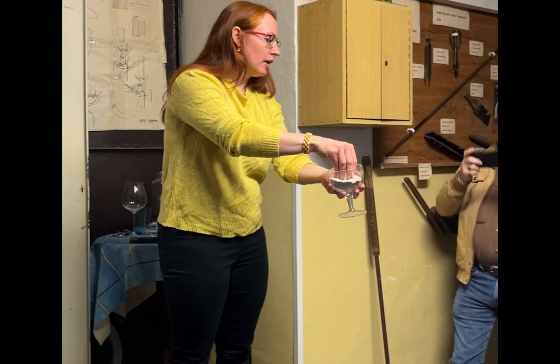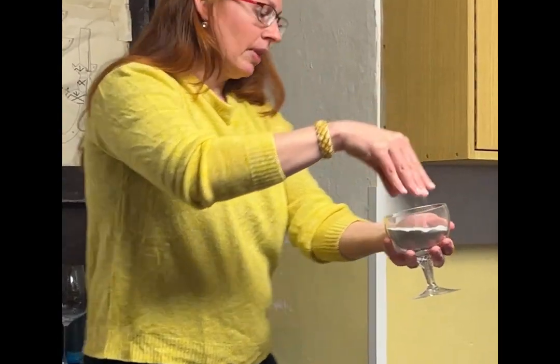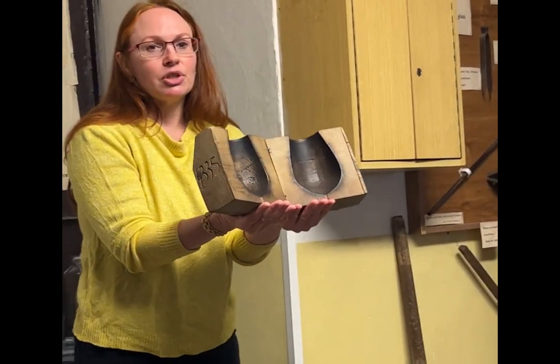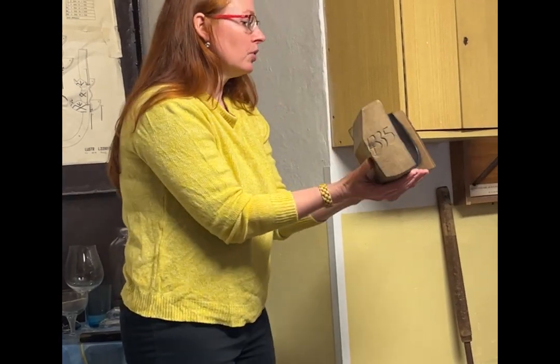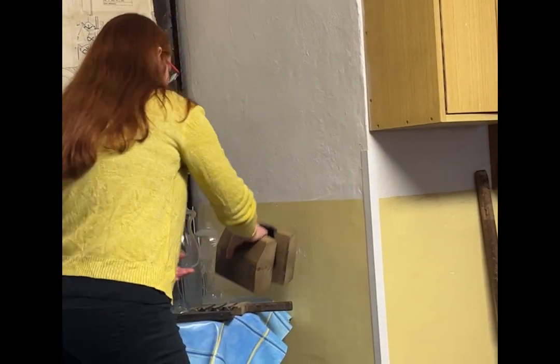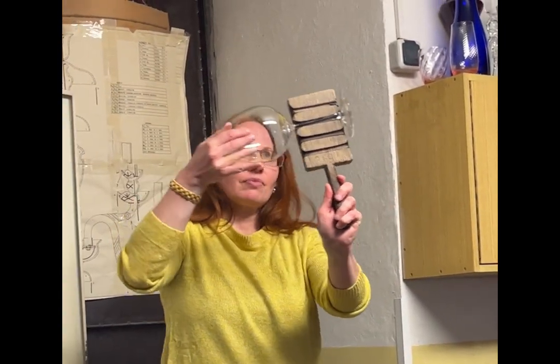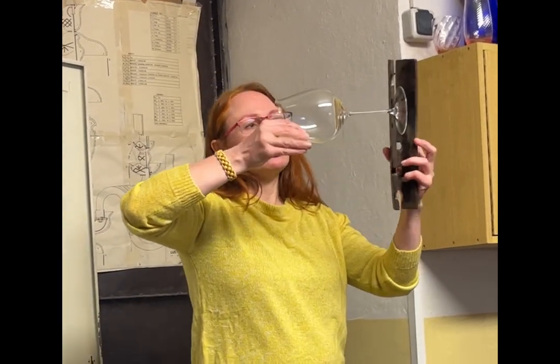These are the wooden molds made from oak wood. The molds are only used for two or three days because the glass is so hot it is still burning — after a few days, every glass comes out a different size. So they have a special group here that makes new wooden molds every day, and the blowers have to turn with the pipe constantly.